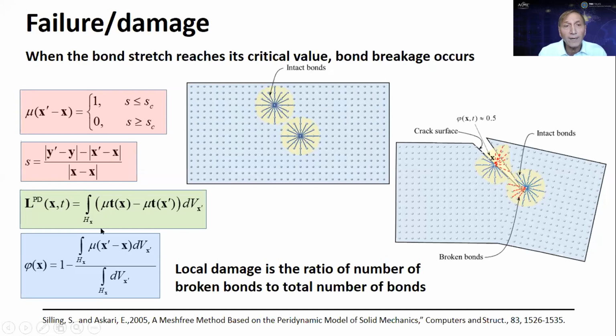And the fact that you have one bond broken doesn't mean that you're going to have a crack. So we also have a measure of the damage. So we'll look at the ratio of broken bonds to the total number of bonds associated with a particular point here. If you see this point here, initially it has basically full interactions. And now here, when the crack appears, this point X lost half of its interactions on the other side of the crack surface. So if it's about 0.5, then we have a crack surface. And the main idea in this case really was introduced by Silling and Askari in 2005.